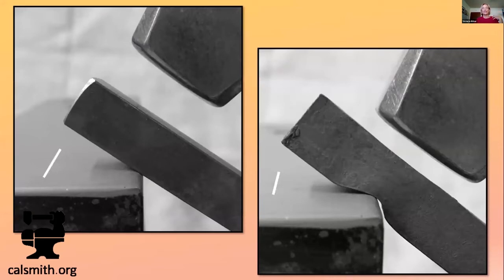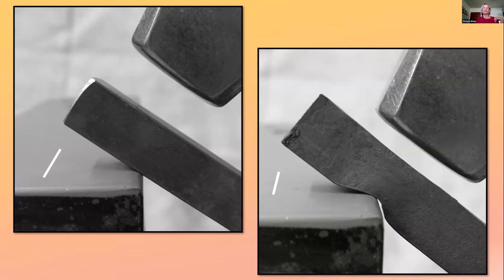So to set down the first part of your box jaw is going to be more of a fullering maneuver, but you are going to be on the near side of the anvil on a rounded edge. And you're going to lay off an inch and an eighth. The box jaw gets a little thinner on the edge and you're drawing it out to the side. So does it need to be any longer than that? And I know I'm only talking about one sixteenth of an inch, but if you want these to fit up right without having to do a whole lot of rasping, the one and one eighth inch to start is going to be helpful.